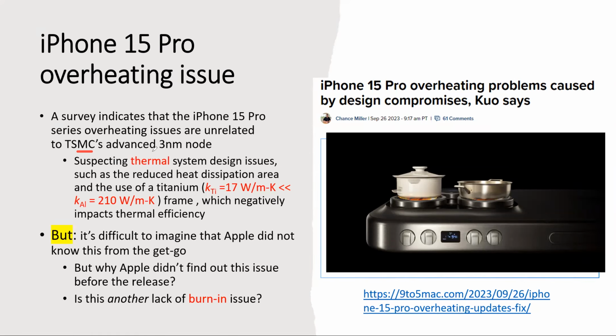However, some people believe that this is what they find out. It's not TSMC 3 nanometer fault. TSMC actually had a great party inside their own to celebrate their high volume manufacturing of the 3 nanometer node, and they're very happy with it. However, they later found out that there could be some problem in the design. One of the reasons is the titanium case they put it on is super nice, super pretty. But unfortunately, titanium thermal conductivity is not that good.